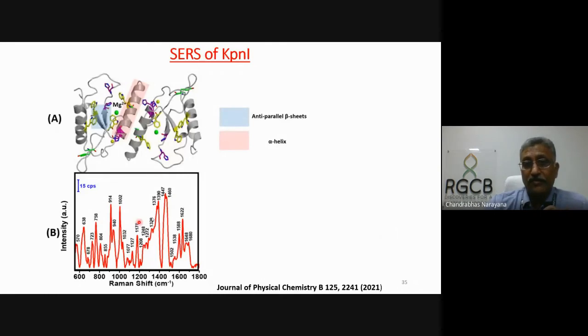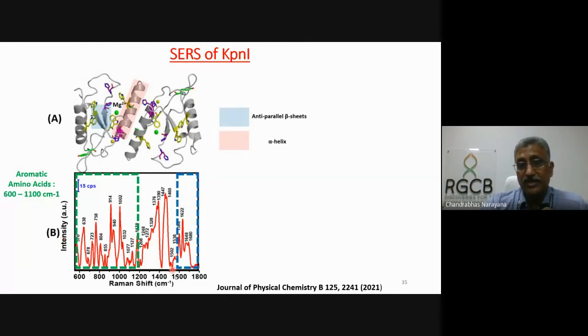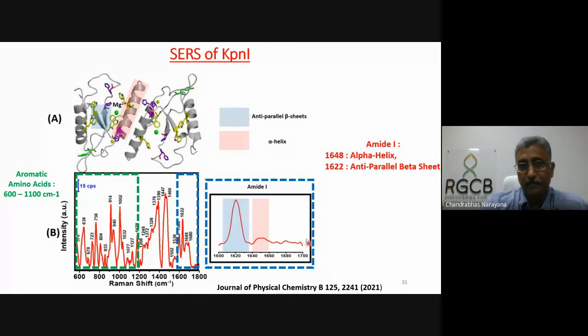Once we know that, we do the Raman spectra, and we can see that most of the low frequency modes are associated with aromatic amino acids, but the high frequency region around 1600 is because of the amide region. I have color coded the beta sheets and alpha helix, and this is the dimer of that. You can see that this is the beta sheet, which is coming closer because this is the EDD region. And this is the alpha helix region, and that's what is seen.